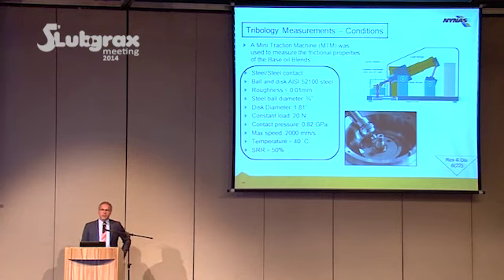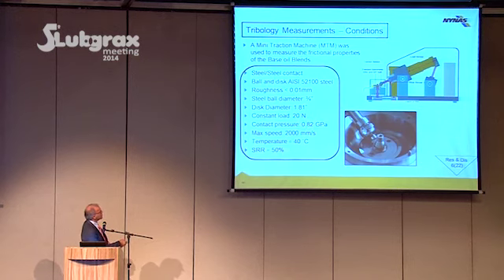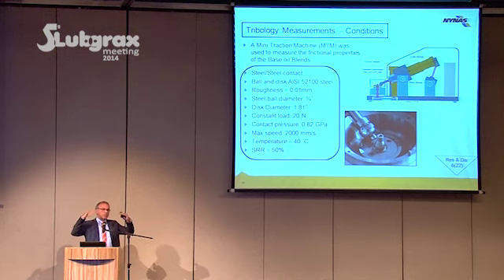This is the tribological test we use, the test method, MTM machine, mini traction machine. Most of these numbers are standards. This number is chosen, 20 Newton, which if you translate it to the contact pressure means 0.82 gigapascal. And the test has been performed at 40 degrees C because at 40 degrees C we had 150 centistokes for